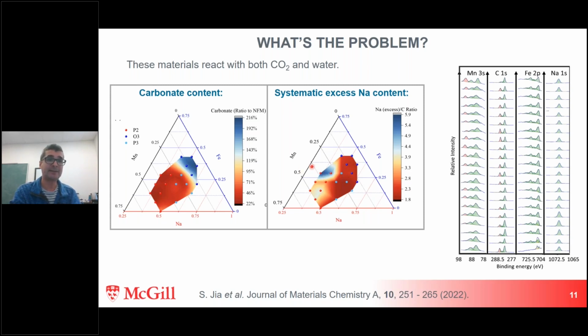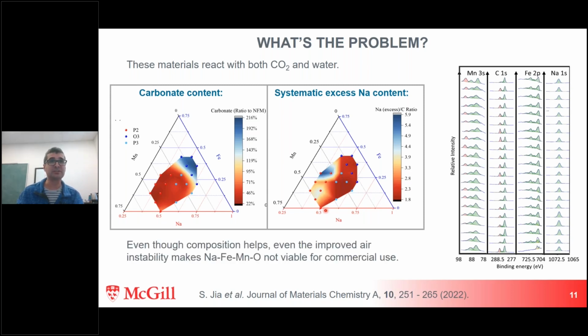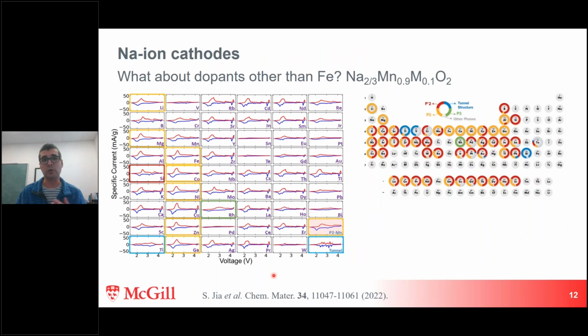So up here, we're reacting strongly with water. So we react with carbonate when we have too much iron. Over here in the P2 phase, we react with water. Down here, that's mitigated, but we're still reacting with water. So the star that we made down here is much improved for air stability over some of the other compositions that have been studied before, but it's still not good enough. It's still not stable enough to be commercialized. So we want to look to see if doping can be the answer.